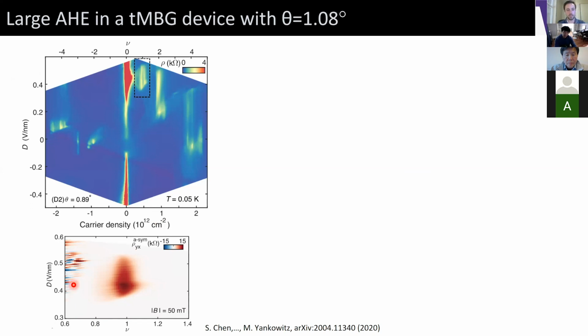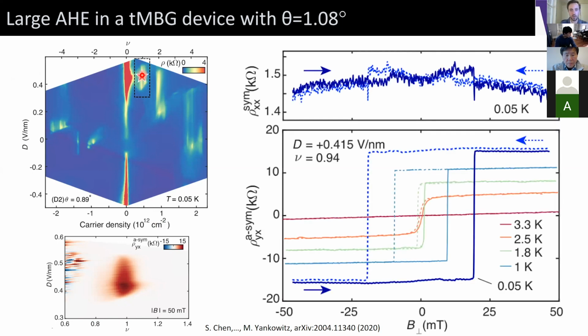So that suggested that there's some sort of spontaneous magnetic ordering in the system. And indeed, if we park the gate precisely at this point and sweep the magnetic field up and down, we see this very obvious hysteresis loop in rho YX, and also some weak hysteresis in rho XX, which is a hallmark of ferromagnetic ordering.